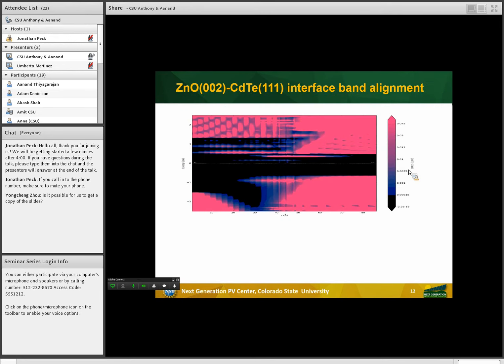Initial modeling efforts have focused on simulating a zinc oxide and cadmium telluride model because of the inherent complexity of the ternary alloy that is magnesium zinc oxide, and also because of the fact that zinc oxide up to magnesium have the same wurtzite crystal structure.